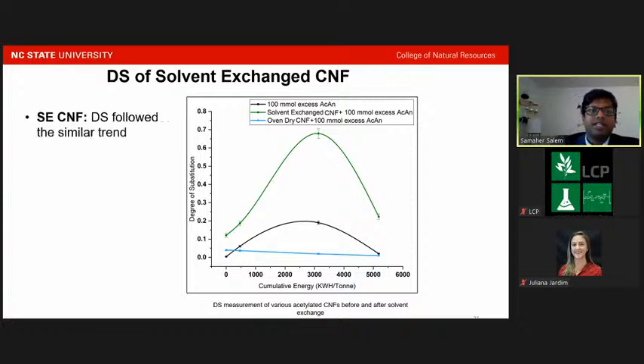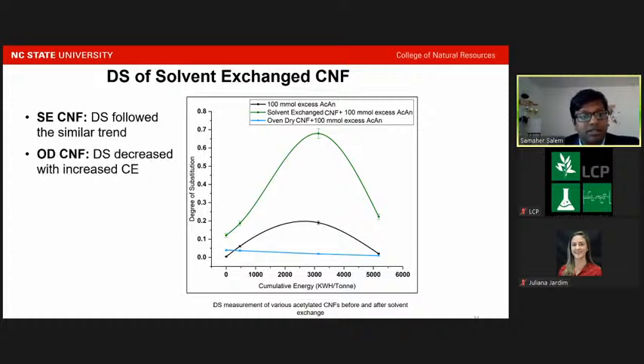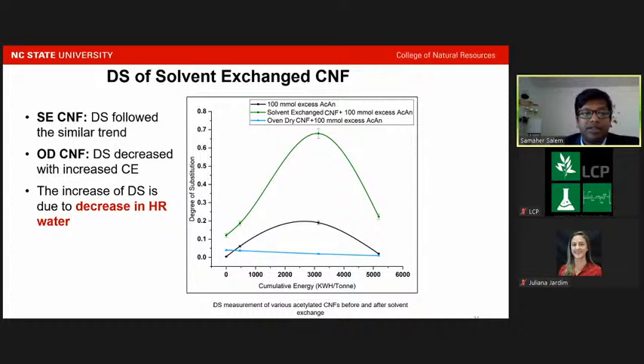And we could say that for the solvent exchanged CNF, the trend of the reactivity is the same. The reactivity increased initially, and after reaching a maximum, the reactivity of the nanocellulose decreased. For the oven-dry sample, the degree of substitution decreased with the increase of the energy. And the increase of the degree of substitution was due to the decrease in the hard to remove water. So when we exchanged the solvent with ethanol, there was much less hard to remove water, almost none. So we could say that there is a high jump of the degree of substitution. The reactivity of the nanocellulose really, really increased for the solvent exchange compared to the water containing nanocellulose.